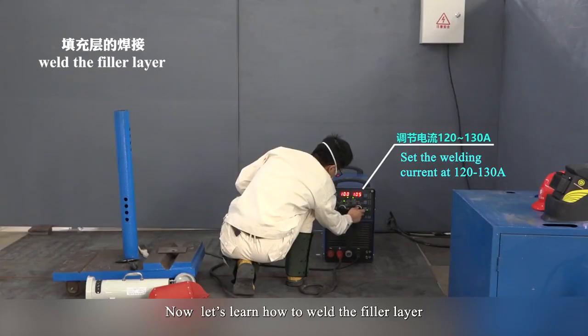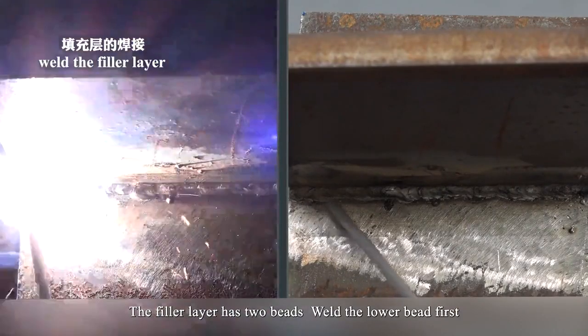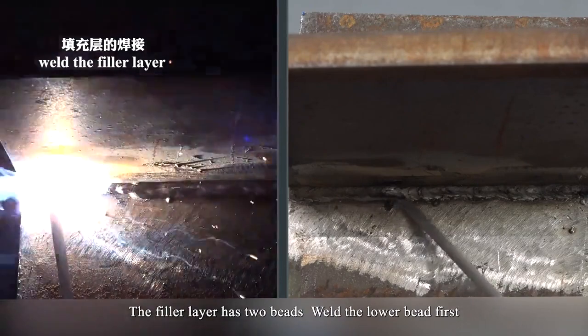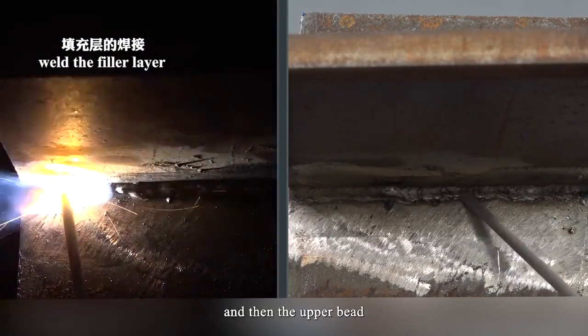Now, let's learn how to weld the filler layer. Set the welding current at 120 to 130 ampere. The filler layer has two beads. Weld the lower bead first and then the upper bead.